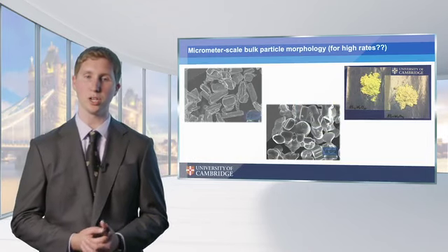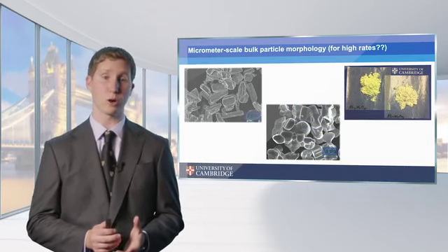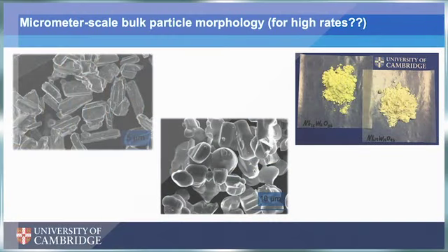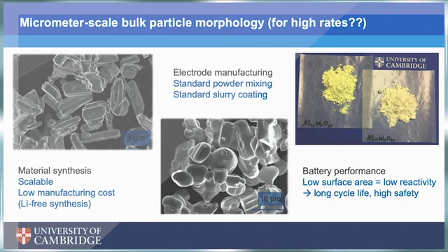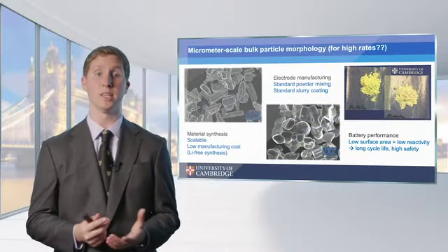And so here we are studying large micron scale particles, sort of the 3 to 10 micron range, fully dense non-porous materials, and we actually observe that they show the extremely high rate performance that we would conventionally only be able to get out of a nanostructured version of something like LTO. And so this gives us several advantages. It has advantages at the material synthesis level, because these powders are easily scalable, from the lab scale up through commercially relevant, kilos to tons.